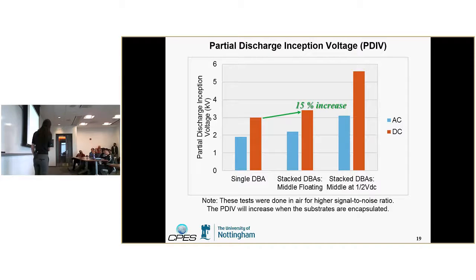And so this is plotting those partial discharge inception voltages for 3 different cases. The blue is for an AC excitation at line frequency. The orange is for a DC excitation. So you can see that when you stack 2 substrates and leave that middle layer floating, you only get about a 15% increase in your PDIV, which is still good, but maybe it doesn't justify the cost or processing of that extra ceramic substrate. But if you connect that middle metal layer to half the DC bus, then you get more than 60%, closer to 70% increase in your PDIV, which is starting to be significant.